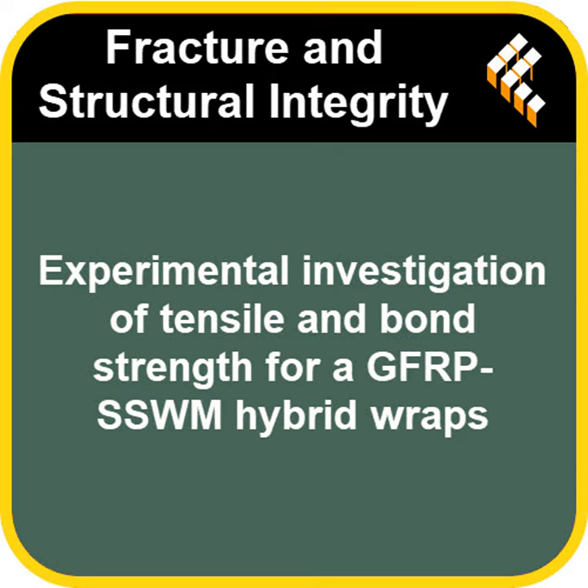And that brings us to this specific hybrid, GFRP plus the stainless steel wire mesh, SSWM. Now, the SSWM part caught my eye. What's special about the wire mesh? I saw something about the cost. Yes. The SSWM brings a lot to the table. It actually bonds pretty well with concrete, which is great, and it behaves much better at higher temperatures. Better than the GFRP. Yes. And then there's the economics. It's significantly cheaper. Roughly INR 650 per square meter. Compare that to GFRP at around INR 1250. So doing the math quickly, that's almost half the price, like 50% less. Exactly. Almost half, which, again, for large infrastructure budgets is a really big deal.